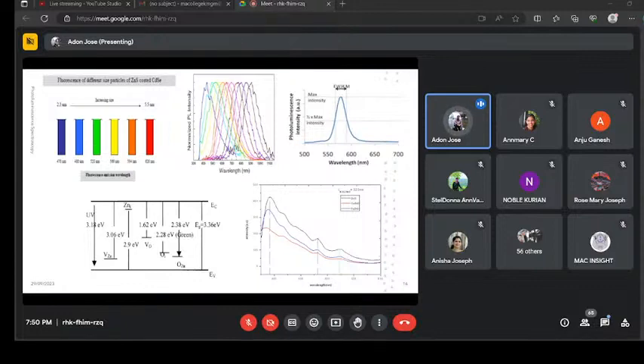It is possible to determine the size distribution of certain samples by observing this full width at half maximum. If we are considering quantum dots, I think if the full width half maximum is greater than 30, then the system is polydispersed in nature and has a large size distribution. Whereas quantum dots having a full width half maximum lesser than 30 are usually preferable for certain practical applications. I already said that the interpretation of the full width half maximum or the luminescence behavior differs from material to material.